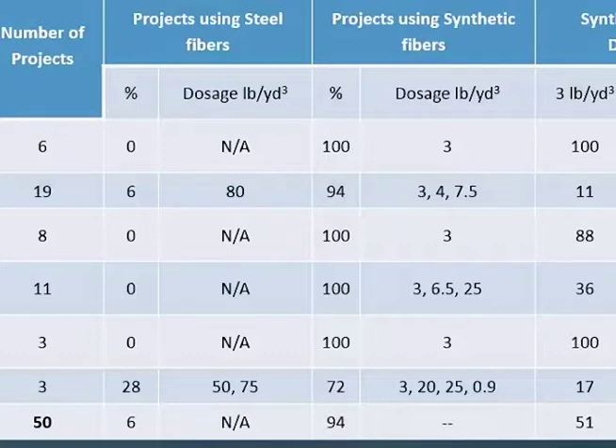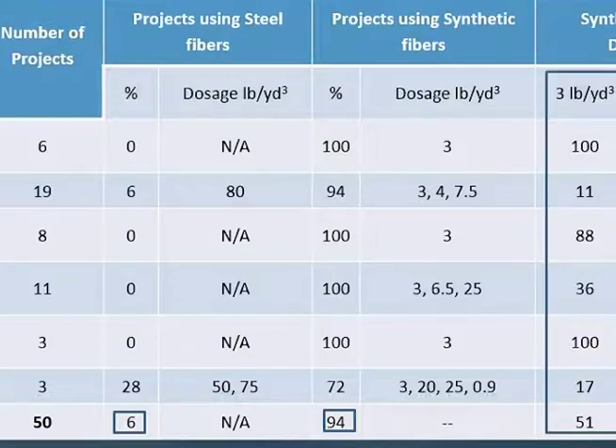So here you can see these are the states that responded properly with numbers. If you look at a few things I put inside the blocks, we have 50 different projects, and out of the 50 projects only 6% were constructed with steel fibers, and 94% with structural synthetic. Then we also asked what doses they use, and most of them responded 3 pounds per cubic yard. We also asked how the dose was selected. We probably did not get a conclusive answer, but an answer like, okay, the other state used 3 pounds, so that's what we have also used, 3 pounds per cubic yard.